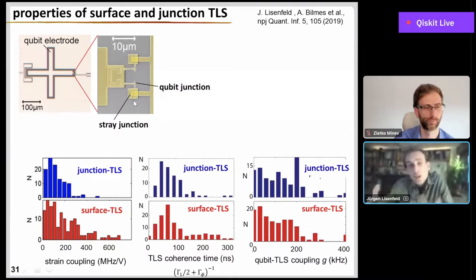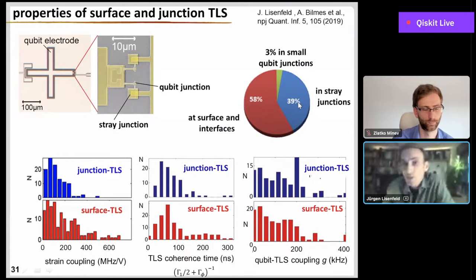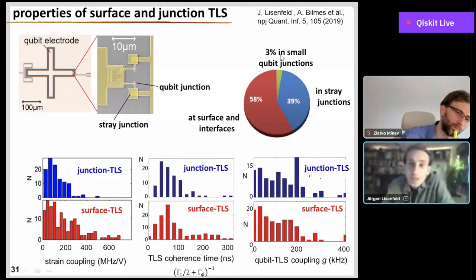And if you make it very large, then you can be sure that it will not be a part of the qubit dynamics, but it still contains a large tunnel barrier with a lot of defects. And actually, these are all the defects which are only in the stray junction. So actually, our statistics at the end looks like this. We have only a few percent in the small junction, the largest part on the electrodes, and of course, a significant part in these stray junctions.